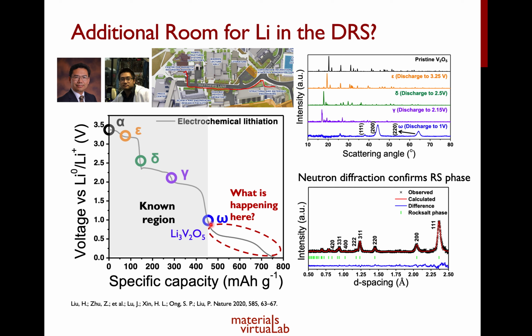Now, what they did that previous people never did was to try to further lithiate it. Okay, so they continued to lithiate it all the way down to 0.01 volt, and to their surprise, they found that there's actually a significant quantity of capacity below 1 volt, right? And this is actually very surprising. Okay, so where does this additional capacity come from? Now, even more importantly, this additional capacity is very interesting for anode applications. Okay, what you notice is that this additional capacity occurs at an average voltage of about 0.5 to 0.6 volt versus lithium plus.